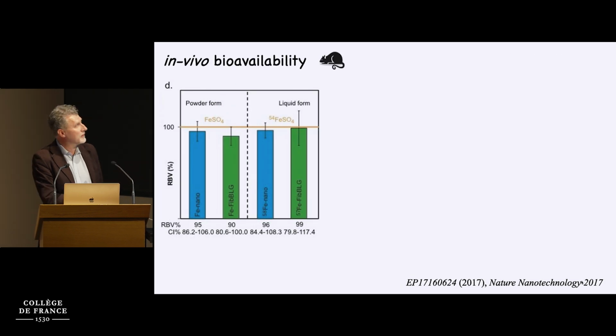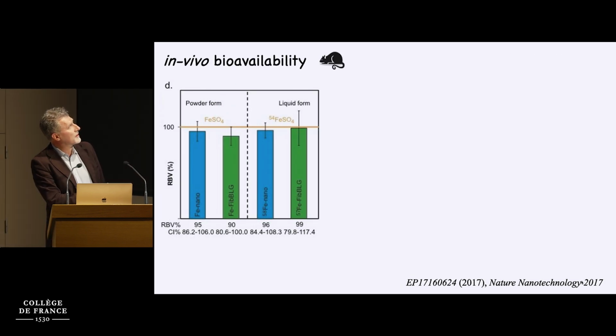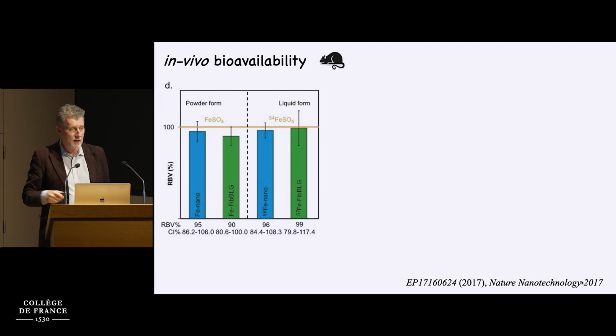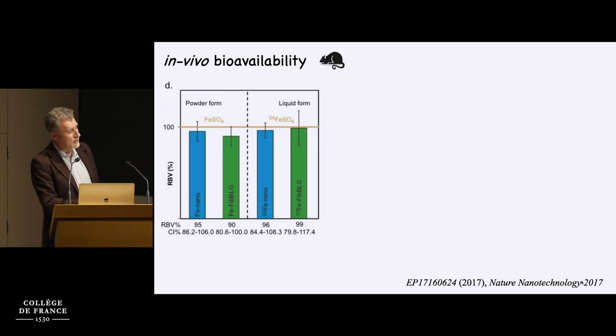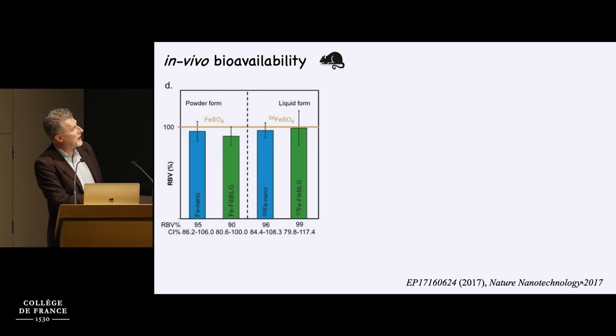And if you now check the bioavailability, you see this is the gold standard, iron sulfate, which is 100% iron 2. It cannot be used, or is used, but the impact in food fortification is really strong sensorially, and many women who are under this treatment, especially if they are pregnant, have to stop the treatment after a few days because it is a very strong compound with a horrible taste. Still, it serves as a benchmark, and you see the green is the fibril. You reach a bioavailability which is close to the one of iron sulfate. In this case, we're talking still about rats.